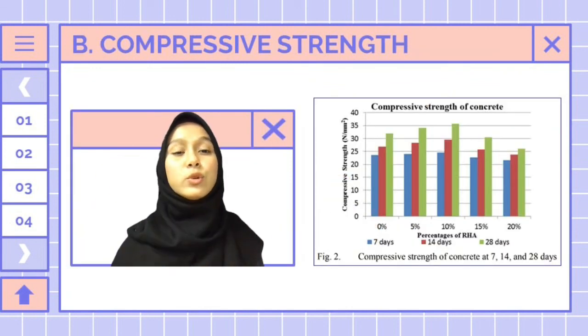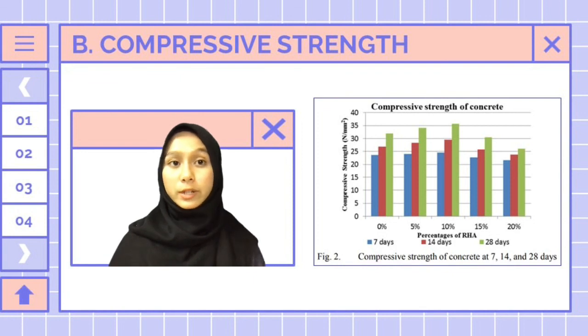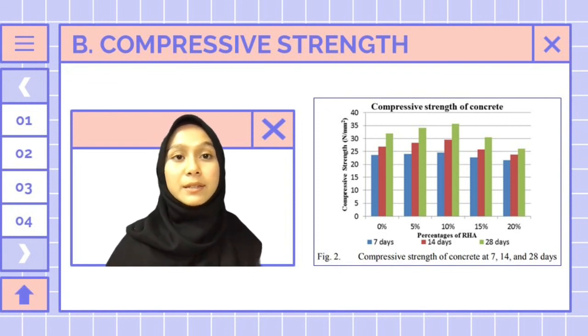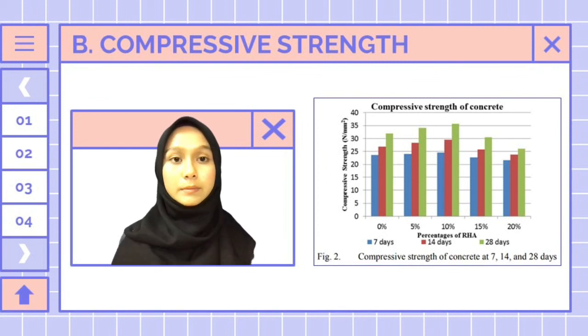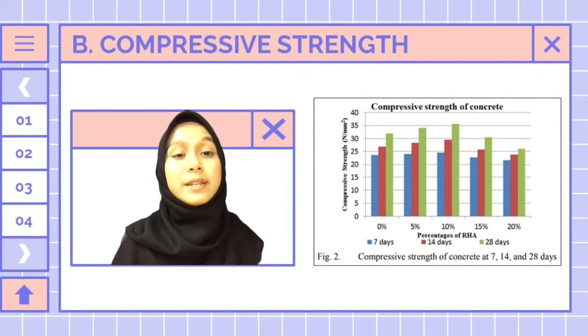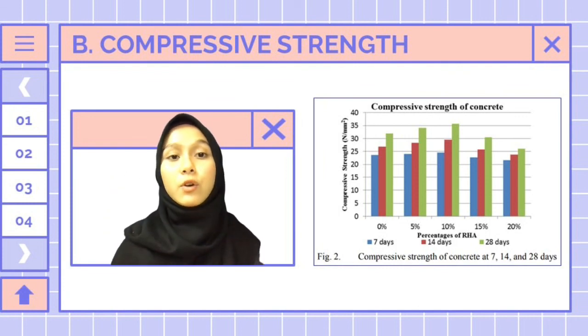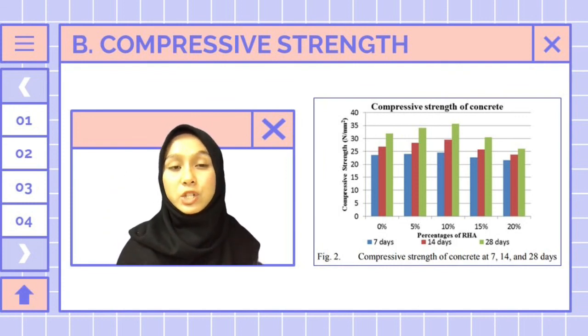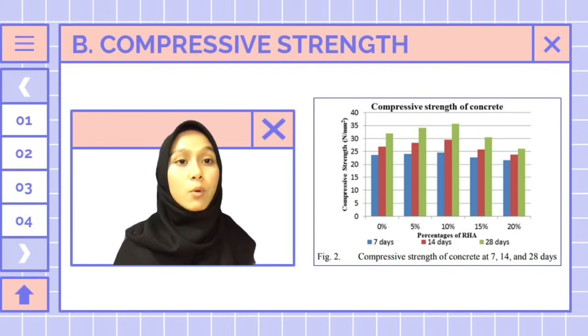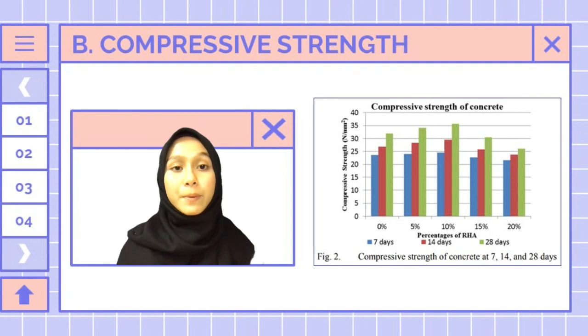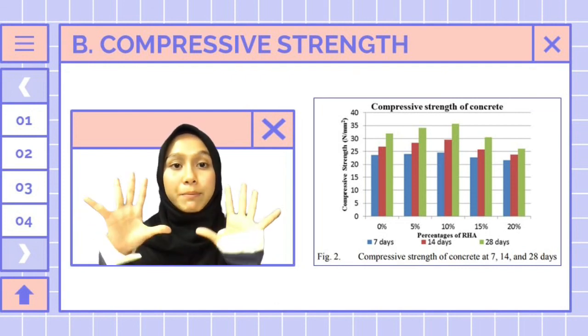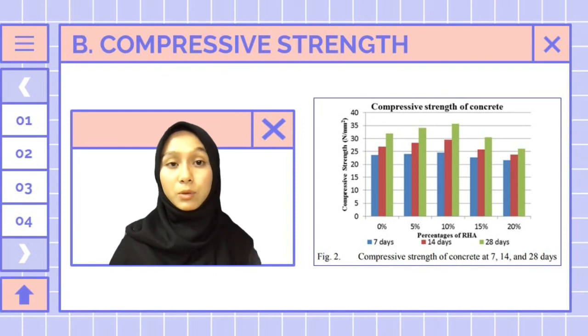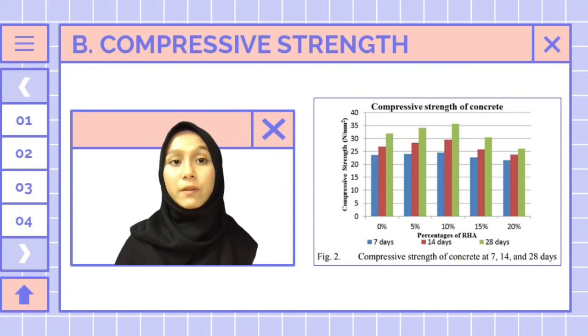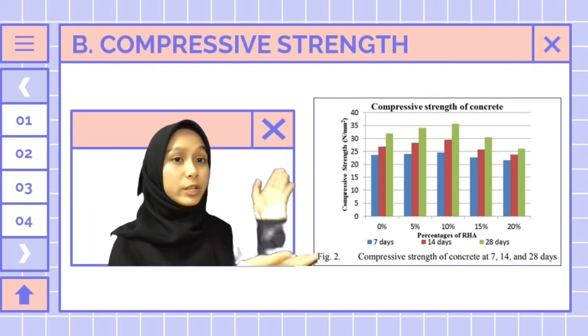Next, Test B, which is the compressive strength test, was conducted on cubes with volume 100 mm times 100 mm times 100 mm by using different RHA percentages. Three specimens were cast for each proportion, and ultimately an average of the values of the concrete specimens was taken as the final result. The compressive strength was maximum at 10% of RHA used as cement substitute material in the concrete, and minimum at 20% of RHA at 7 days, 14 days and 28 days. As you can see, the results are shown in figure 2.